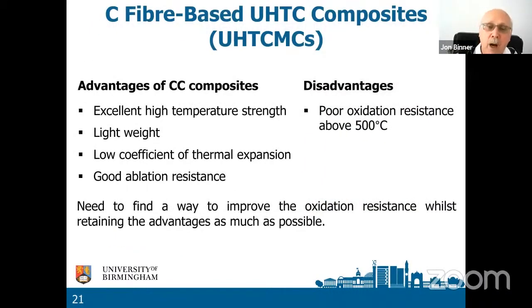So the carbon-carbon composite has excellent high temperature strength. It is very lightweight. It has a lovely low coefficient of thermal expansion. It has excellent ablation resistance, but it has extremely poor oxidation resistance above 500, and we want to heat these materials to 2,500 or 3,000 in air. So we need to find a way to improve the oxidation resistance.